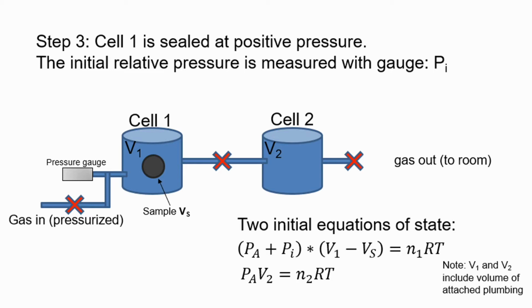Step 3 is to close the gas input valve and measure the initial pressure using the pressure gauge. This gives us our two initial equations of state, which will be used later to derive our sample volume. A note here is that V1 and V2 include the volume of the attached tubing.